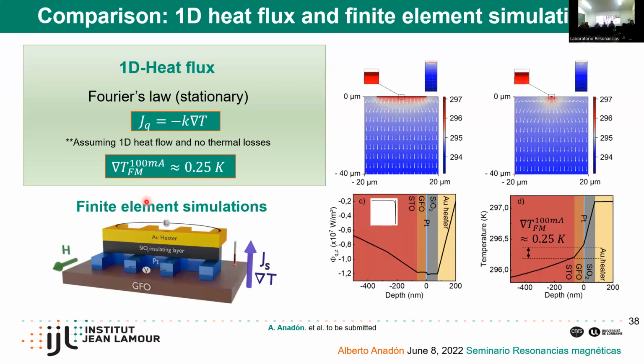We can do also finite element simulations. And if we look at the device, basically what we observe is that this is the heat flux profile. So the heat flux is producing the gold heater. This is why it's increasing here. Then it's mostly constant through the whole device in the GFO, for example. And then when we reach the substrate, since the substrate is much bigger, then the heat flux goes through all the substrate and is very soon almost zero, as you can see in the inset here.